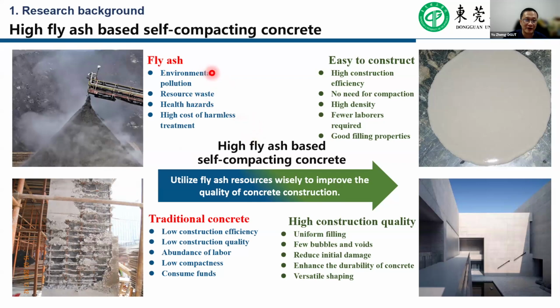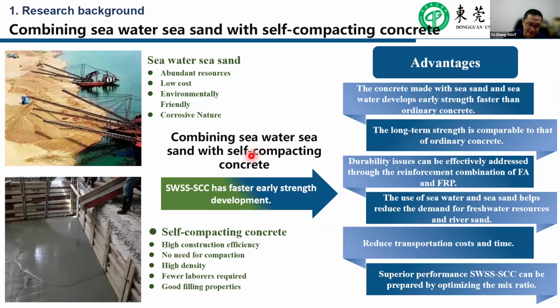We can find that if we use fly ash to replace the cement, to produce high volume fly ash self-compacting concrete, compared to traditional concrete we get uniform filling, fewer bubbles and voids, reduced initial damage and enhanced durability of the concrete. Therefore, when we extend this research to combine the seawater and sea sand with high volume fly ash or high volume industry byproducts self-compacting concrete, we find that the concrete made with seawater and sea sand develops early strength faster than ordinary concrete, and the long-term strength is comparable to ordinary concrete. Furthermore, the durability issues can be effectively addressed through the reinforcement of the FRP.